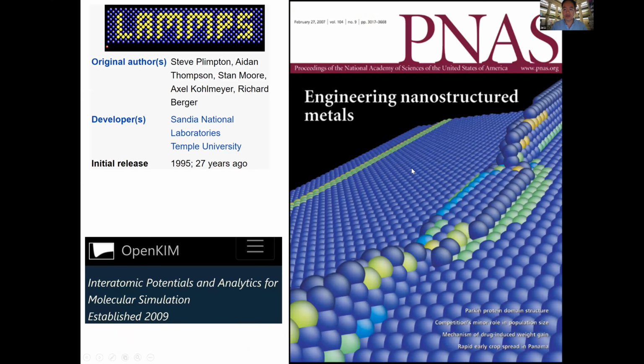So when we try to deal with realistic microstructures, what you see here is a lattice dislocation being absorbed by a coherent twin boundary. So in all kinds of materials problems, we need to deal with tens of thousands of atoms, and it's not sufficient to use the ab initio potential. So generally, we use so-called empirical potentials, and there has been a lot of good work in this field. For example, this OpenKIM database was really important for the community.